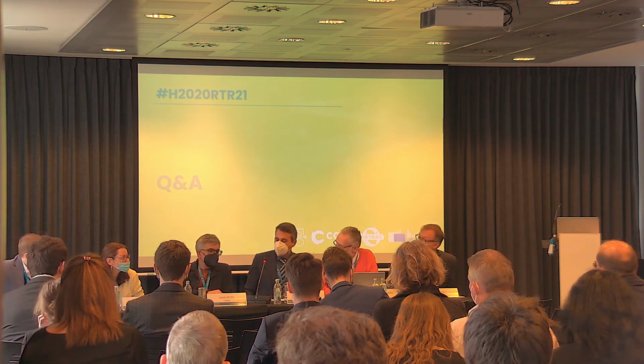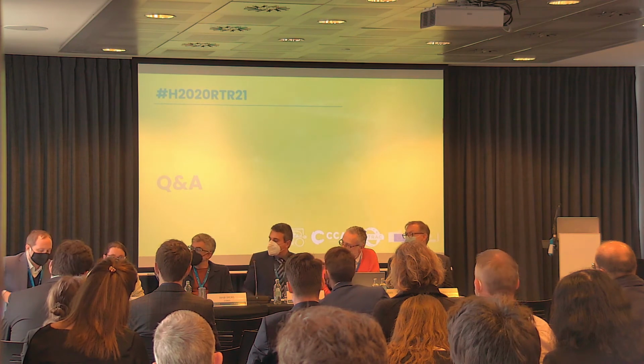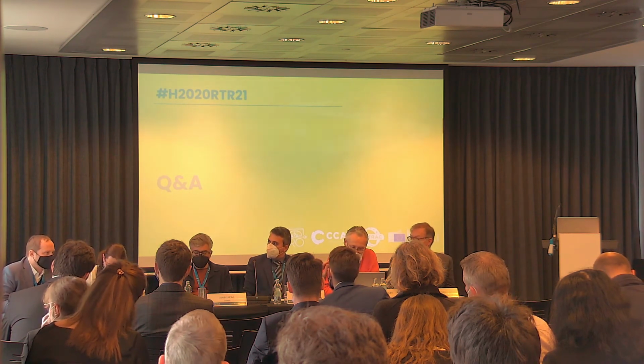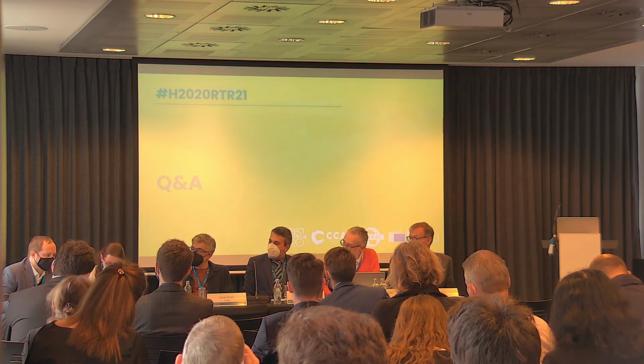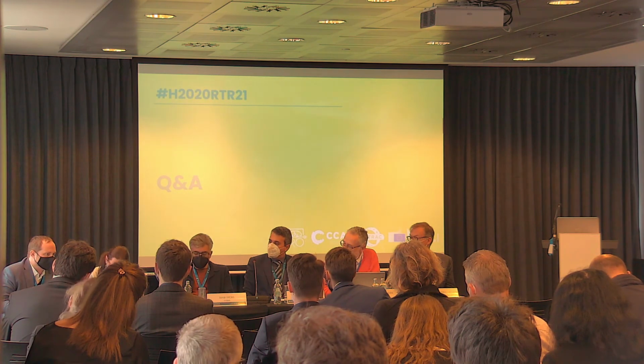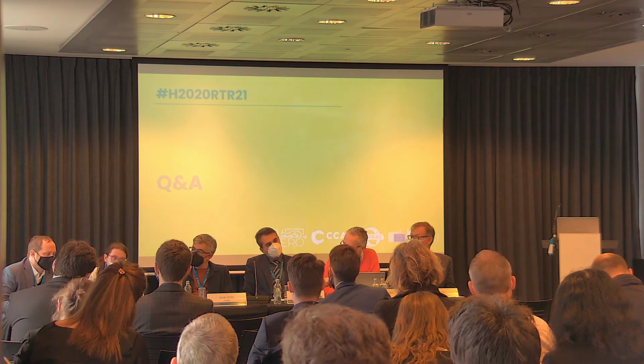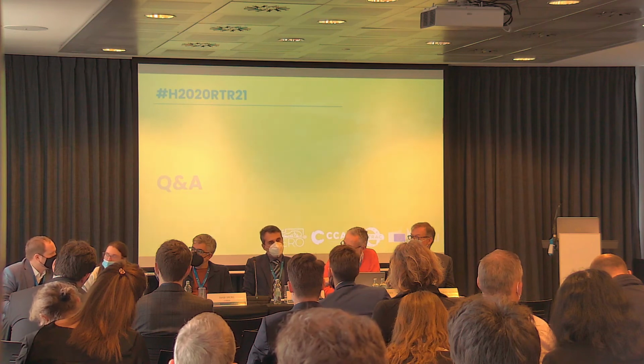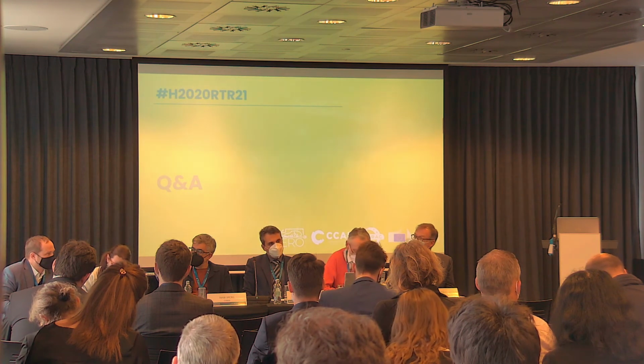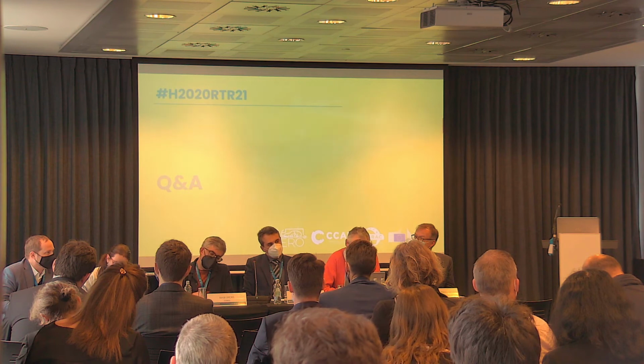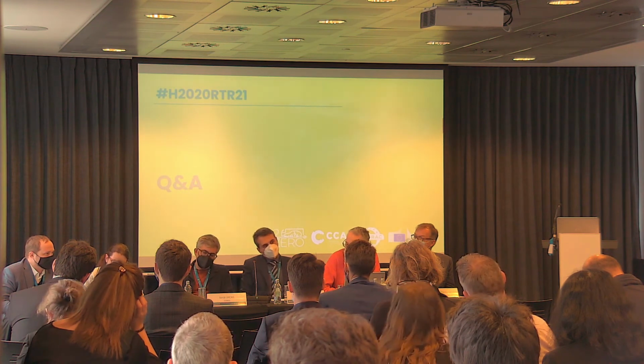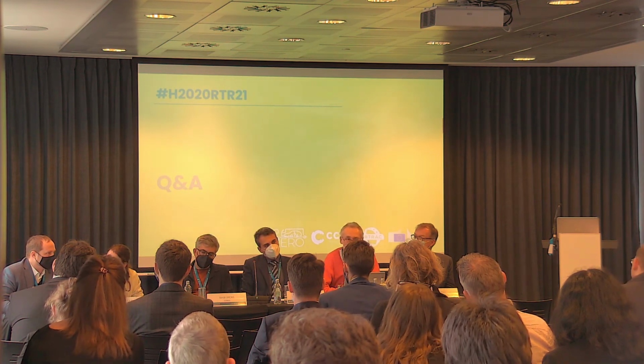Anyone want to add something? For lithium sulfur, we are trying both cylindrical and pouch. It seems that cylindrical is not a good option for lithium sulfur. To give you an idea, for lithium ion in 18650 format, you reach 3 ampere hours of nominal capacity. With lithium sulfur, you will be at half of it.